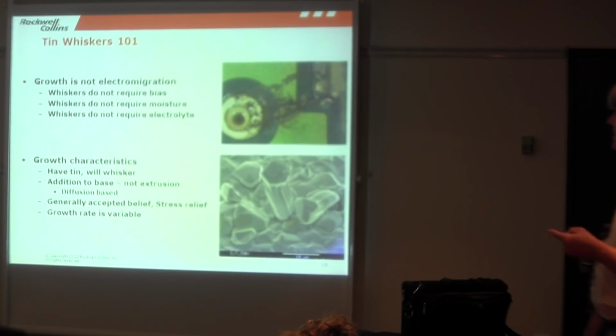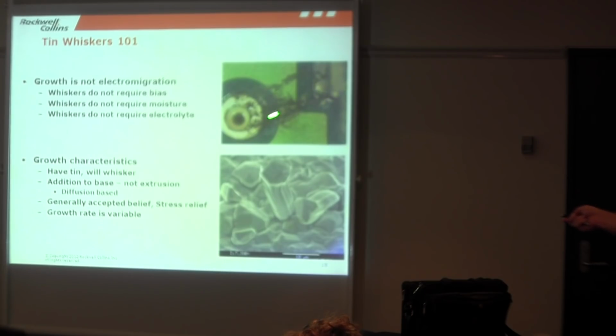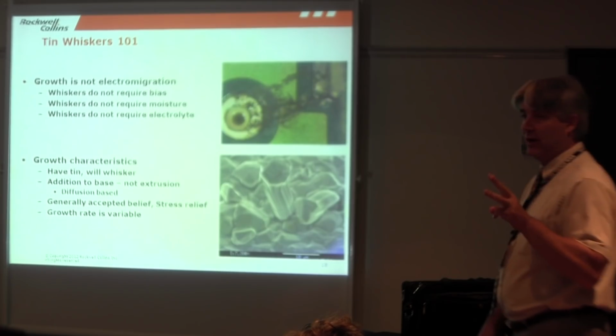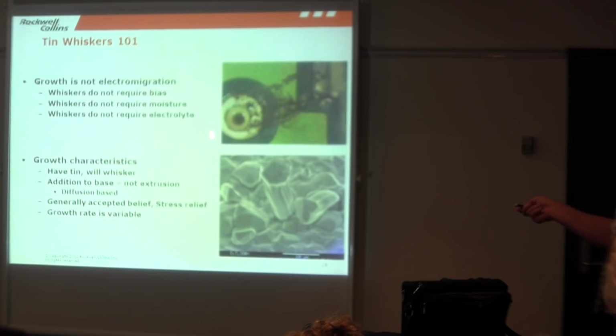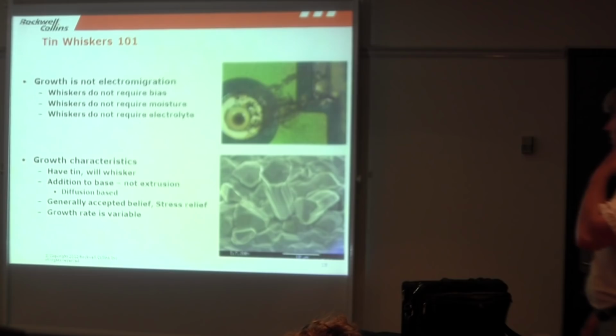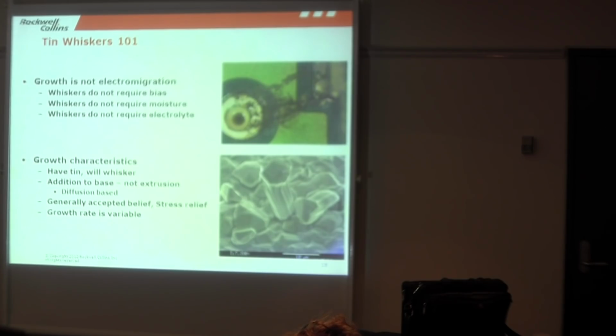Tin whiskers are not electromigration. Everyone has seen where you get a dendrite growing. Whiskers don't need a bias, they don't need moisture, and they don't need electrolyte. And to get electrochemical migration, to grow dendrites, you need those 3 things to make a battery. We do not get those with tin whiskers. Tin whiskers can just grow.